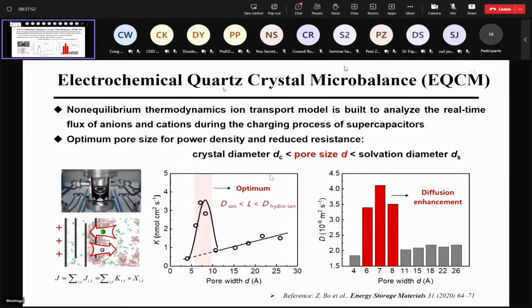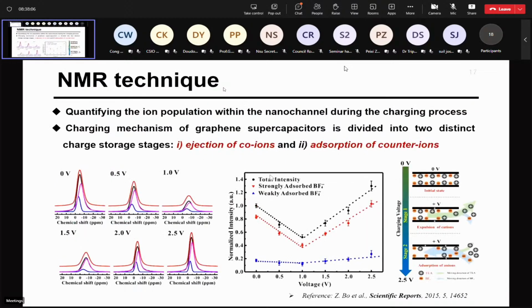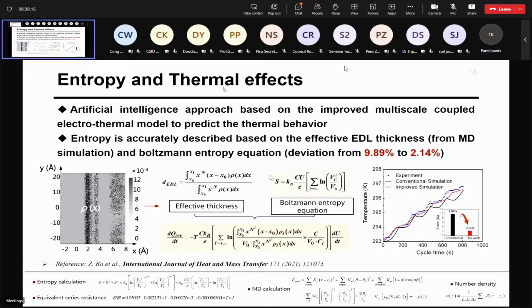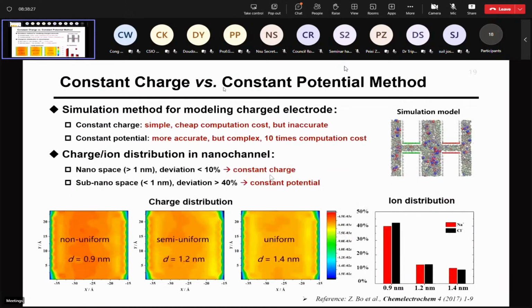This is the experimental work result, and it can be used to determine the optimum pore size to deliver the high power density. Also, we use NMR technology to quantify the ion population within the nanochannels during the charging process. We use multi-scale simulation and calculation work to determine the entropy and the thermal effects in the supercapacitors. We also discussed the possibility of using the constant charge and constant potential method to calculate the ion distribution and the ion transport in the nanopores.